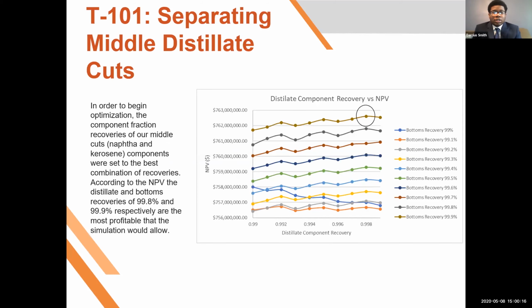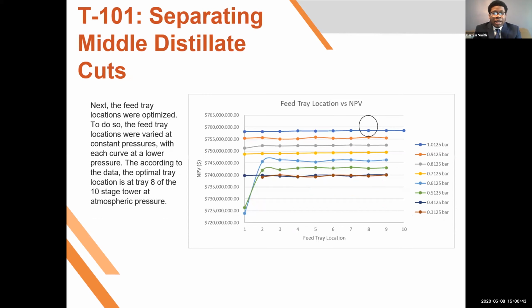So moving on, we decided to see how to optimize our distillation towers. In our first tower, we decided to first see what our optimal specs are as far as purities. As you can see, we have a purity of 99.8% on our distillate and 99.9% recovery in our bottoms. Using that purity spec, we decided to see what the best location for our trays is and at what pressures to run them. And it was shown that for the first tower at atmospheric pressure with 10 stages, the optimal feed tray was at tray 8.